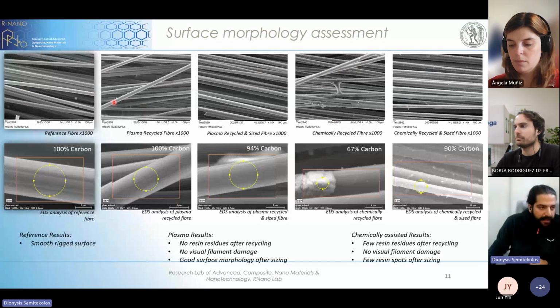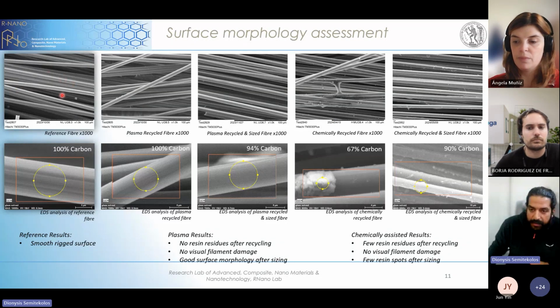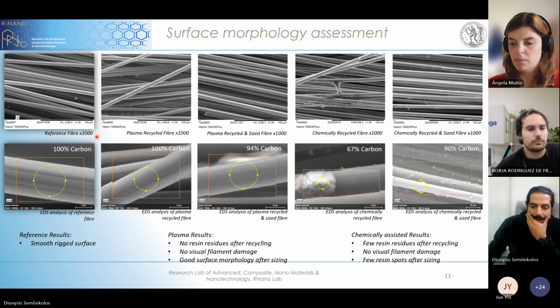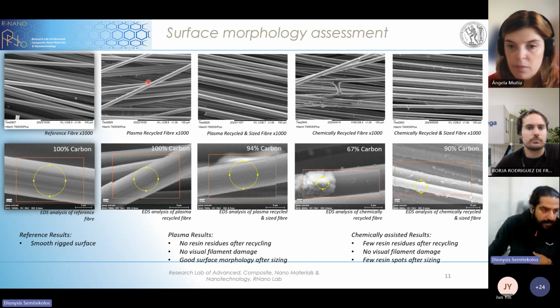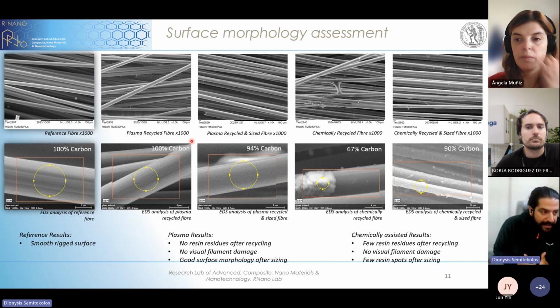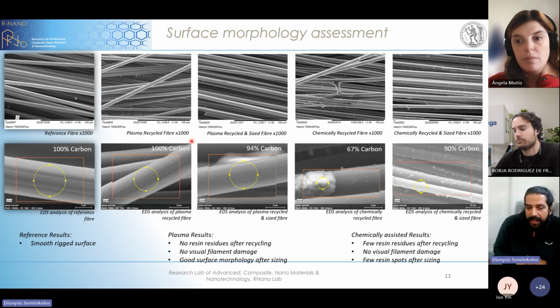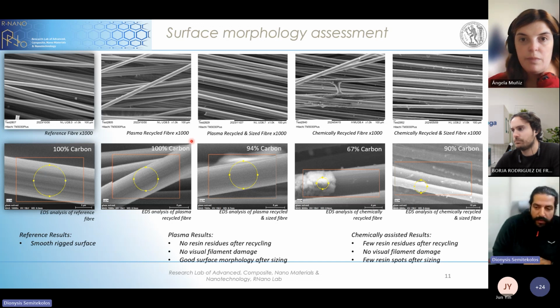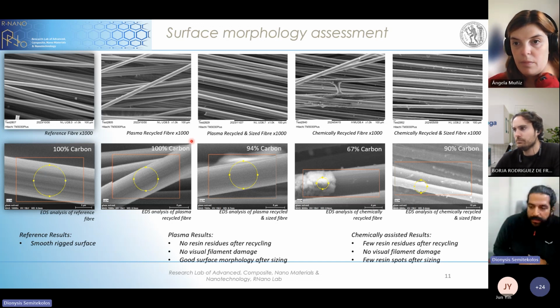Then some technical results. We've seen before, and we see now, how the virgin fibers look under the microscope, and with the EDX analyzer we can determine the carbon or the oxygen content. So besides the morphological indication, we can also have quantitative information about the presence of resins, since we know that carbon fibers are mostly made out of carbon with a very low content of oxygen, which is related only to the particles that exist on the surface from the surface treatment.